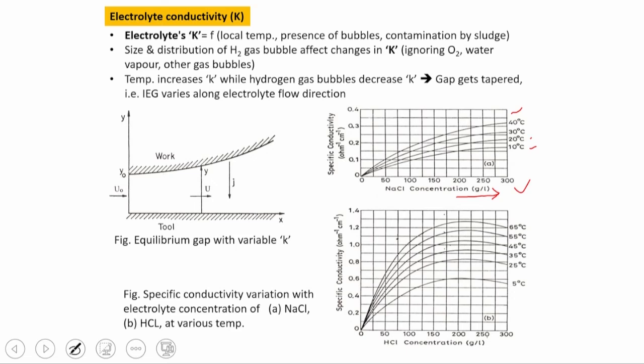Same case for this HCl solution also. If we increase the concentration of this HCl solution, then the electrical conductivity increases. And also if we increase the temperature of this electrolyte, from 5 degree to 65 degree, you can see electrical conductivity increases. So electrolyte conductivity is a function of temperature, and also a function of the presence of bubbles, hydrogen gas, and contamination by sludges. Because sludges are there, they contaminate the entire electrode gap. So if more sludges are there, the electrical conductivity of this electrolyte will change.